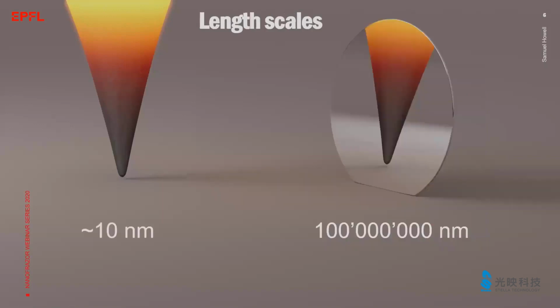It's worth starting with a look at the two extremes in terms of the length scales. The tip apex of a thermal scanning probe is on the order of 10 nanometers and determines the resolution. The other extreme is a substrate. Let's assume we use a 4-inch silicon wafer as a substrate. Hence, the size of the substrate is 10 million times larger. This has two important implications. On the one hand, it takes a very long time to pattern a 4-inch wafer with a single tip due to the scanning speed and also the size.